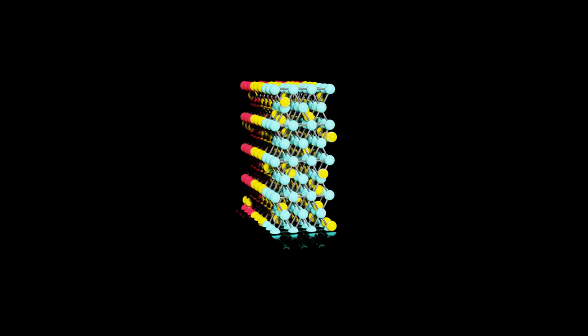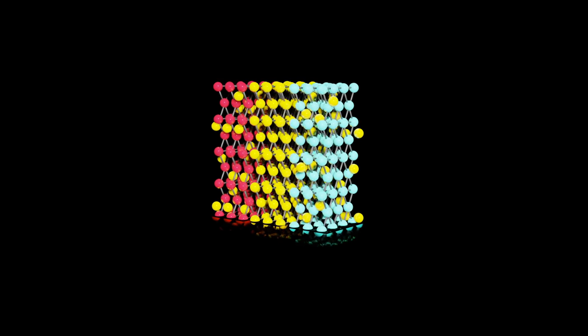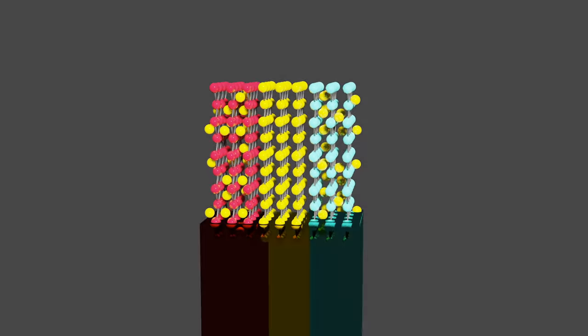What's much more easy to handle is a gradual change, so that's where these interfaces are very tricky. There are some interesting ways to solve it — for example, if you were to inject some of the electrolyte material into the cathode, especially near the interface, and slowly phase it out further out, then you would allow the material to have a more gradual step from cathode to electrolyte. And the same would be true from the anode perspective.